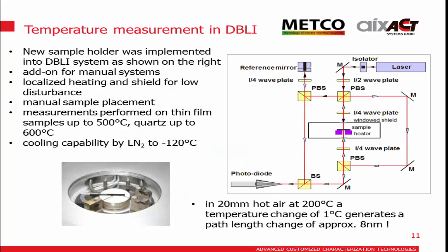Now the challenge is to do this under temperature, because we have a quite long beam, and as you've heard, the refractive index of air changes and has a lot of influence. That's why we made a very small volume, which allows us manual measurements on small pieces that can be heated, and to do this under temperature as well.